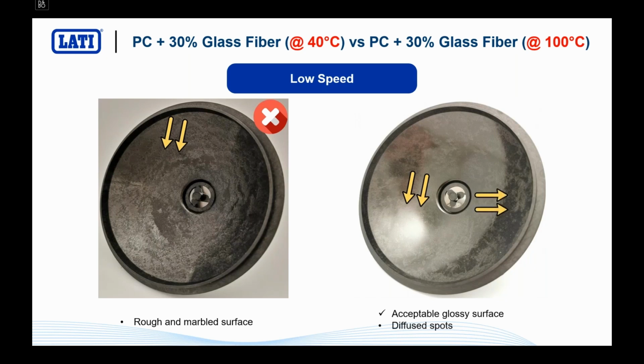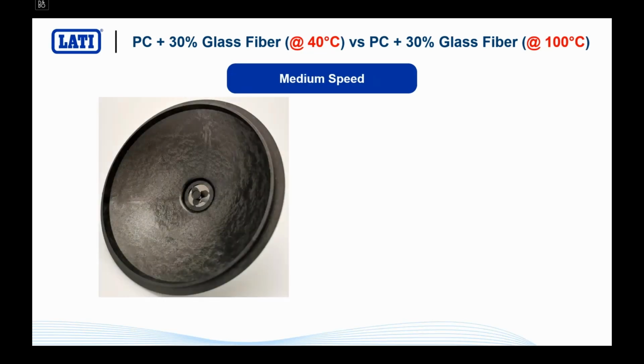You still have some spots here and there, but you have a relevant effect of the tool temperature. Remember what we have seen with the polyamide 6 with kaolin, how relevant was the effect of the tool temperature actually. Let's try to increase the speed. Let's see what happens if we put more energy in the melt, if we put more stress in the melt plastic.